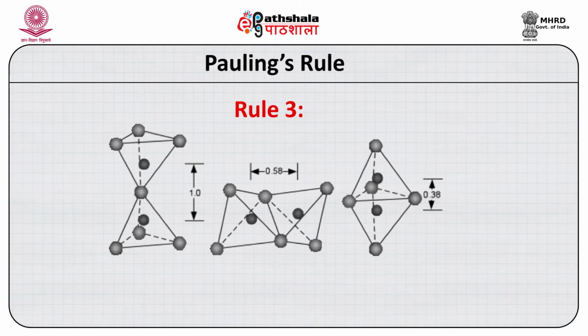When coordination polyhedra share corners, the cations are farthest apart, and this is followed by sharing of edges, and as we know, the repulsion of the cations is least when they are farthest apart. So, this leads to a relatively more stable structure. Now, this property is very significant when looking at the properties of minerals, because the property of the mineral is also dependent upon how stable the structure is.